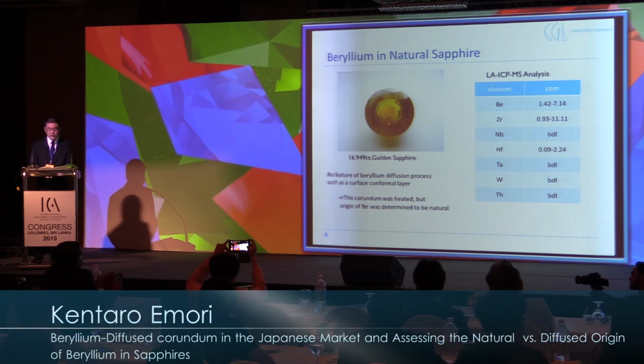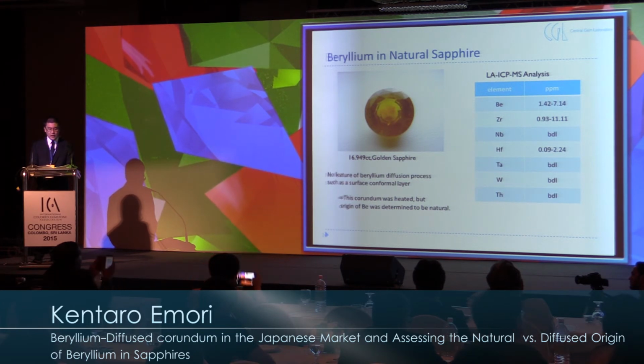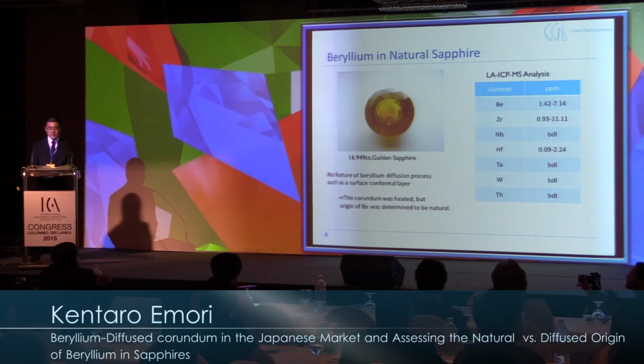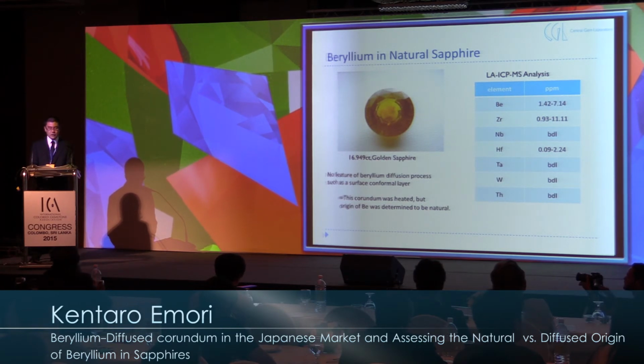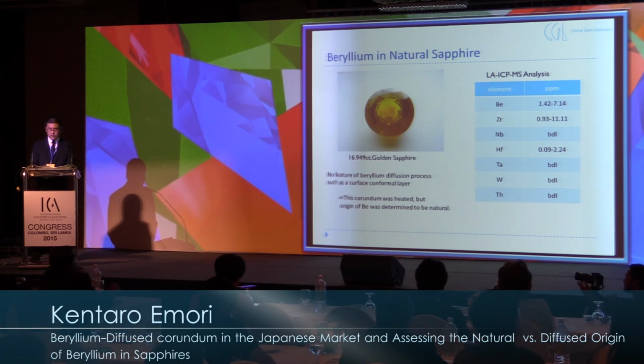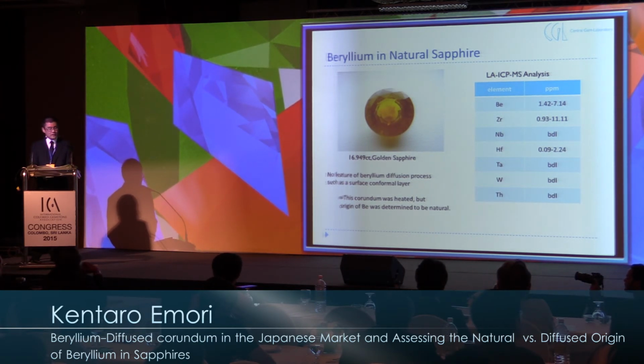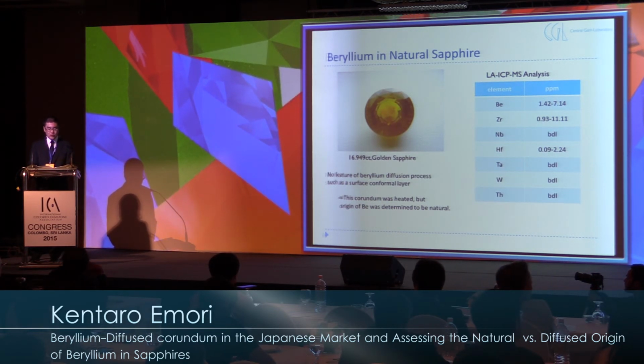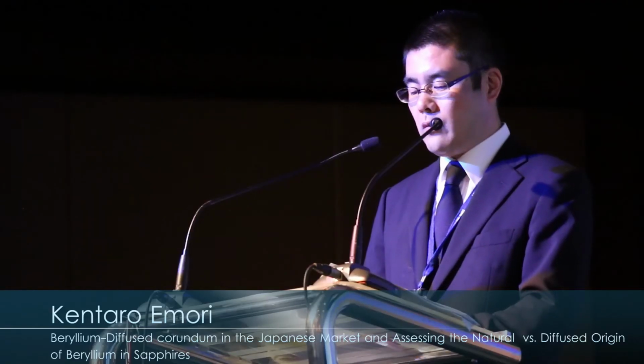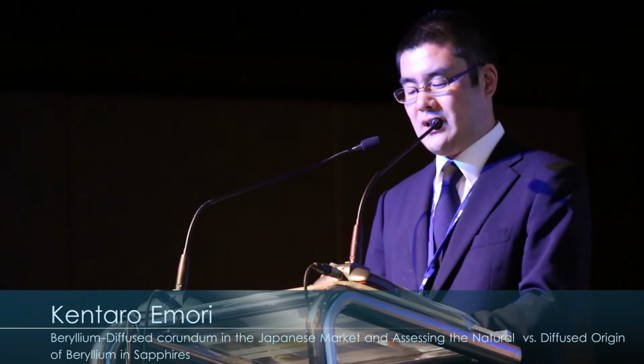This is a corundum crystal which has been identified to contain natural origin beryllium. It is a round mixed cut golden sapphire of 16.949 carat. This corundum has been heated, but it does not show features of the beryllium diffusion process, such as the surface conformal layer. This is a table showing concentration of trace elements. Beryllium contents varied depending on the location, from 7.14 ppm to 1.42 ppm.